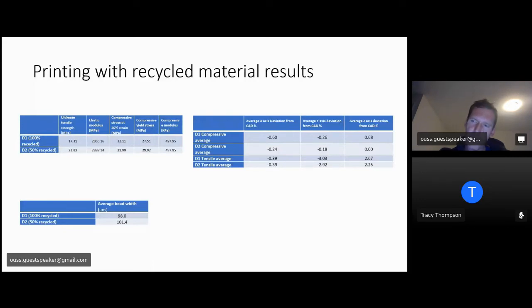It's comparable to old car tires. You know, once they've been used a few times, exposed to a lot of heat and radiation from the sun, they start to crack. And that's very similar to what we're seeing here with the 3D printed materials that are being reused again and again. They start to become more brittle, crack, and they become more susceptible to damage, which is shown there by the stress measurements.